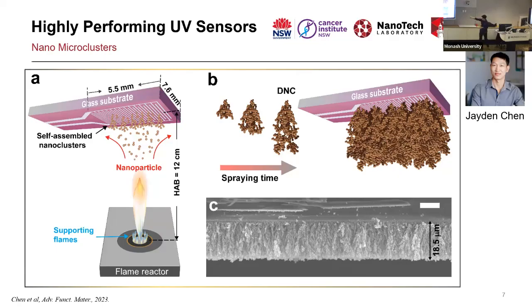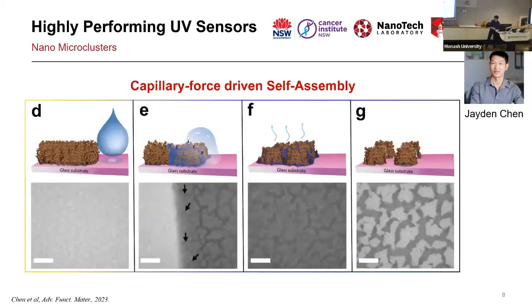So that is the structure, but then what he did, from D to G, is put a tiny droplet of ethanol, not directly on the film but on the side, and let the ethanol be sucked in by the film. This is the ethanol going into the film, and we noticed that the structure significantly changed just by that, and that one is 5 microliter of ethanol. And I'm going to tell you why this is really interesting.